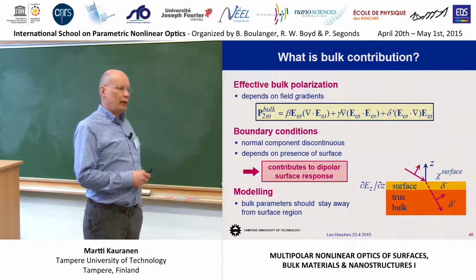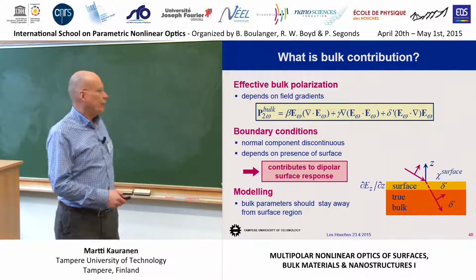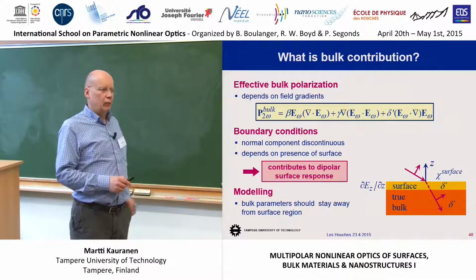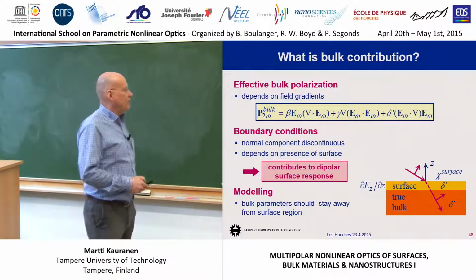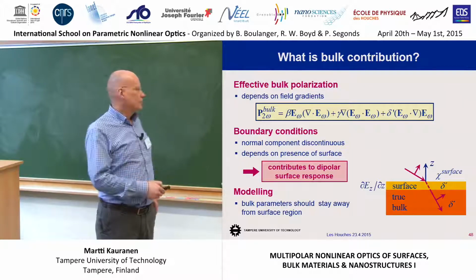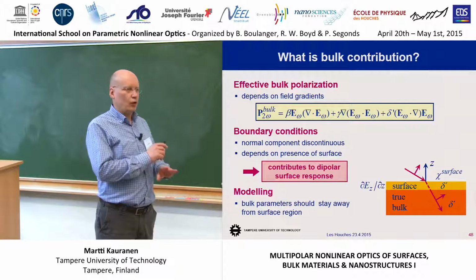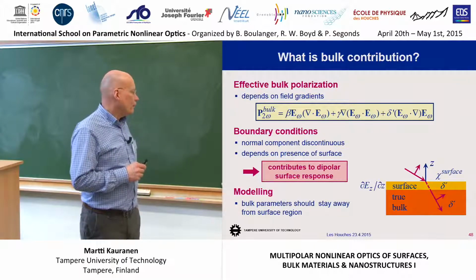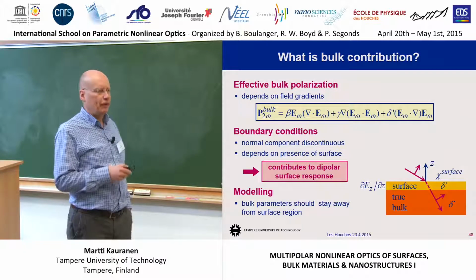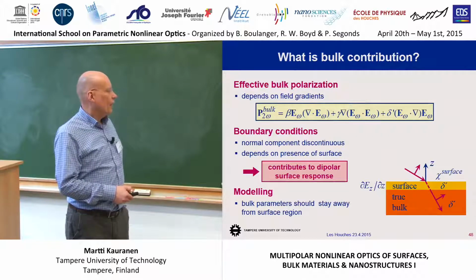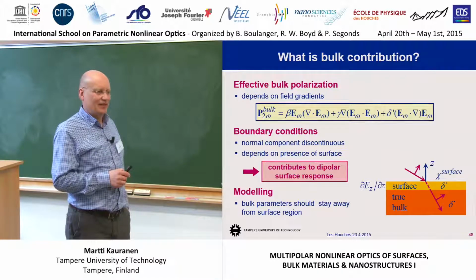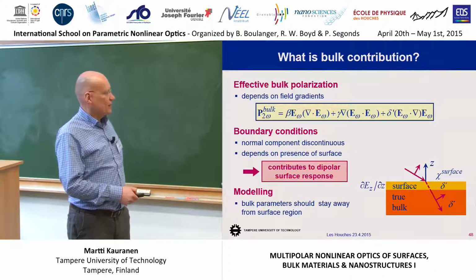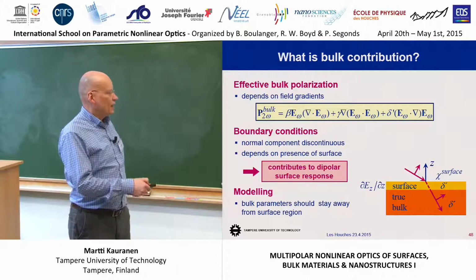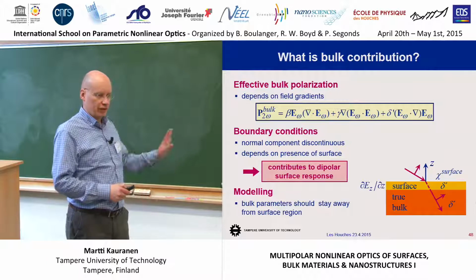The problem is that when people are doing modeling in theoretical models, you can give a number for the bulk parameter, and then you can do another run where delta prime is 0. Some people say that bulk effects are really strong because when they turn delta prime to 0, the signal becomes much weaker. But it's very difficult to figure out, in a number of different papers by different authors, whether they let delta prime interact with the surface gradient. If they do, I think it's wrong to say that there's a strong bulk response. My opinion is that you should keep the bulk parameter away from the surface layer, and then just be happy with the fact that there's some effective dipole tensor for the surface.